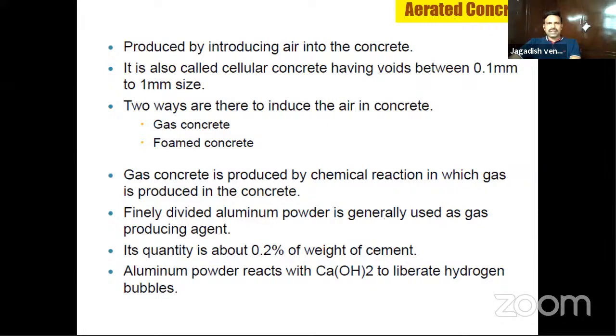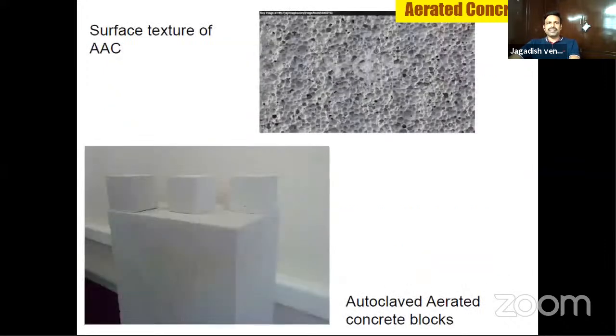And aerated concrete, AAC block is one example of aerated concrete. You can induce the air in 2 ways. One is by incorporating gas. This gas is produced by incorporating aluminum powder into the concrete mix, wherein it is a gas producing agent. You take 0.2% by weight of cement. How it reacts: the aluminum powder reacts with the calcium hydroxide, and it liberates hydrogen bubbles. That's how you can create the voids in the concrete. That's how the density will get reduced.